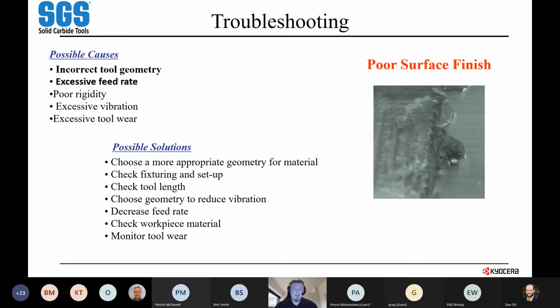Poor surface finish. How do I make my surface finish better? Usually, it's a combination, or individually, the wrong geometry for finishing, or too heavy of a feed rate. Rigidity can be a factor there, but if you're finishing, generally you're not taking that heavy of a cut. So I would hope that at that point you probably have that part dialed out. But it does happen, and sometimes it can just be a worn tool.